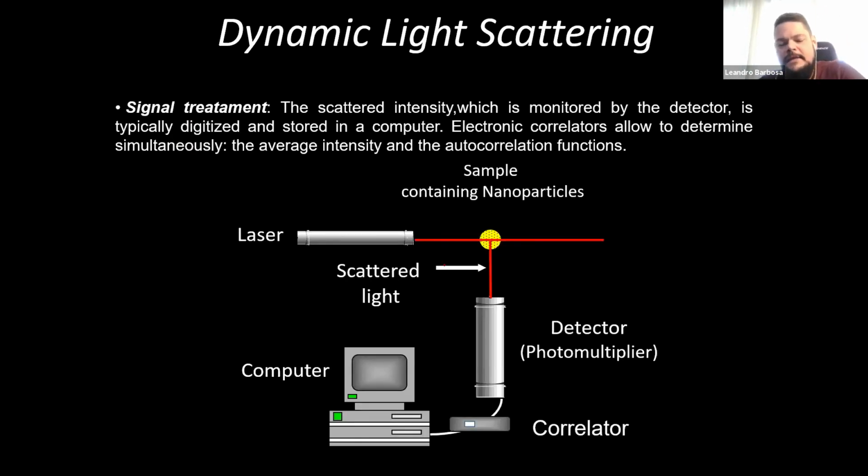And this is the most important thing for DLS. When you develop the physical theory of DLS, the first thing that you write is that I'm supposing that the particle is under only the action of the Brownian motion. There is no other kind of force acting on my nanostructure, my nanoparticle, only the Brownian motion. So you cannot have any kind of interaction between two nearby scattering particles.